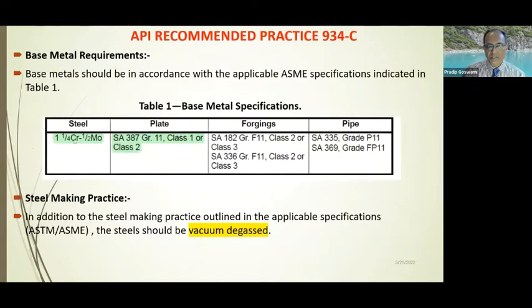And as far as the base material is concerned, typically these are 1¼ chrome half moly. These are A387 Grade 11, Class 1 or Class 2. So Class 1, Class 2 is very well known to everybody. And forgings are generally Class 2 and the matching composition F11, and pipes are also matching composition P11 type.